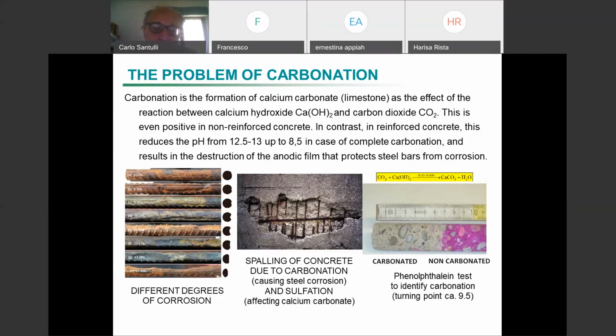You have different degrees of corrosion, which are calculated by the amount of material which is taken away, removed from your steel bar. And what is more worrying is that in this case, we don't have cavities, we have some parts protruding. And this depends on the design of the steel bars. There are a number of types of steel bars. Anyway, we don't do any smooth steel bars anymore because then the interface is so variable, and also because water is able to move around between the concrete and the steel bar. In this case, water has more difficulty to move around at the interface between the steel bars and the concrete.